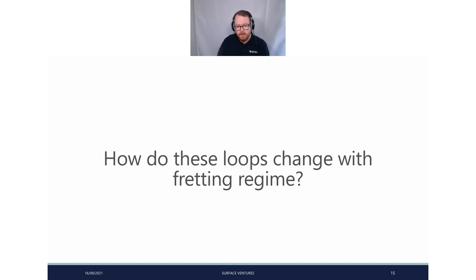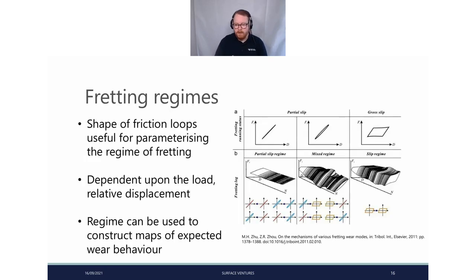So how do these loops change with fretting regime? Again, feel free to put any comments in, but I'm aware of time, and I want to keep moving. So we have different fretting regimes, as I talked about earlier, which are defined by essentially what the actual displacement is and the friction. And there are 3 different shapes that we typically associate. So we have our partial slip regime, effectively not a full hysteresis loop. There's very little area inside that. It can change a little bit, but typically this is the lowest amplitude fretting generally.